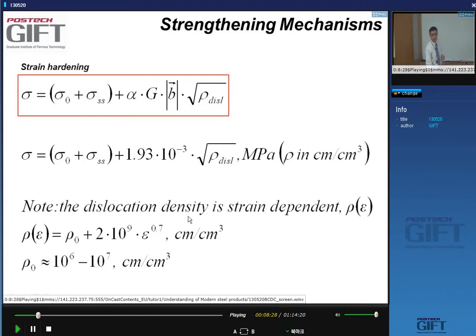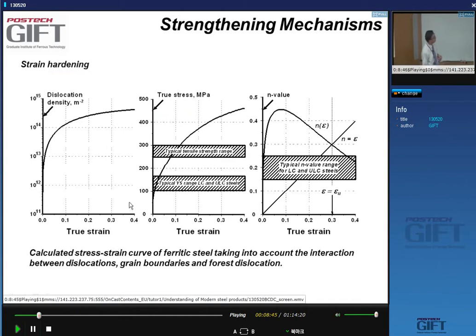And this dislocation density is a function of strain. So the dislocation density will increase with the strain, and some people have developed relations between the dislocation density and the strain. So when you measure a stress strain curve, yes, this is a stress strain curve here, you see that the dislocation density increases. And typically you go from 10 to the 11th to about 10 to the 15th dislocations per square meter.